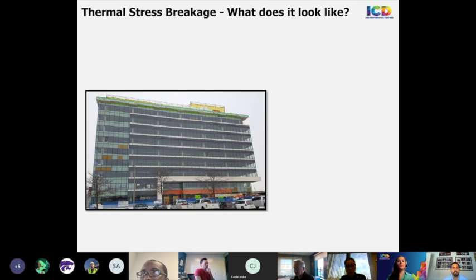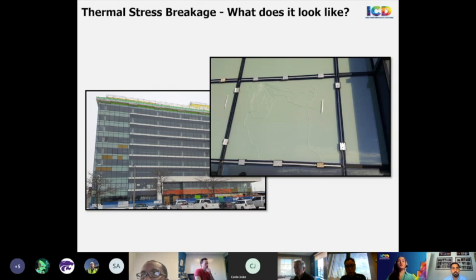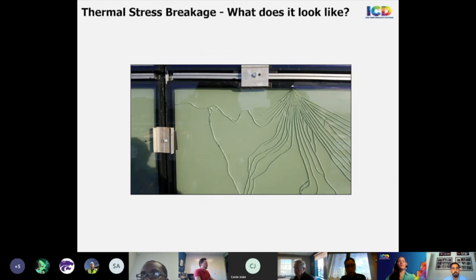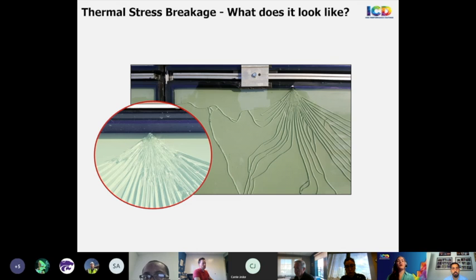So here's just a real life example of a building that had glass that was broken due to thermal stress. So there was an insulated glass unit that was heat treated for the spandrel with a low solar gain low-E coating on surface number 2 and an insulated sheet metal backpan behind the glazing unit. And the inboard pane of glass is cracked with a ceramic frit opacifier applied to surface number 4. And looking closer, we can see the top of that crack and how it branches out at the spacer with temporary support installed to hold the glass in place. And zooming in, you can see the fan, and the branching of the crack is actually starting out above the spacer. So not right at the edge, but within the depth of the spacer and perimeter sealants.